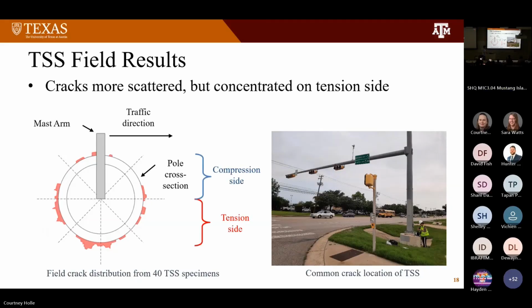For TSS, we follow a similar normalization process. And here what we can see is cracks are more scattered compared to coast, but still they are concentrated on the tension side, which means that, same as coast, the weld toe on the tension side is a critical weak area.